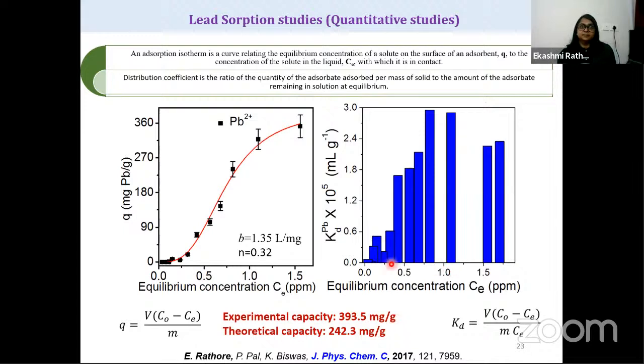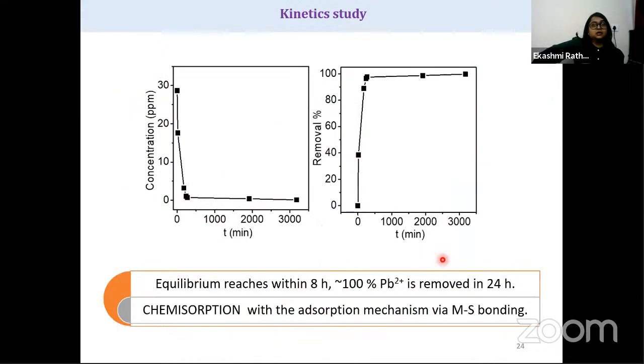Now, to understand whether the material is highly efficient or not, the other parameter is the distribution coefficient. The distribution coefficient should be in the range of 10 power 3 to 10 power 5, and it can be calculated by using this formula. We have obtained very high distribution coefficient values, which tells us that our material is highly efficient in nature.